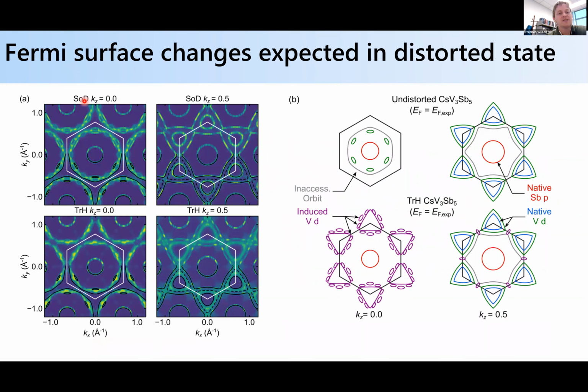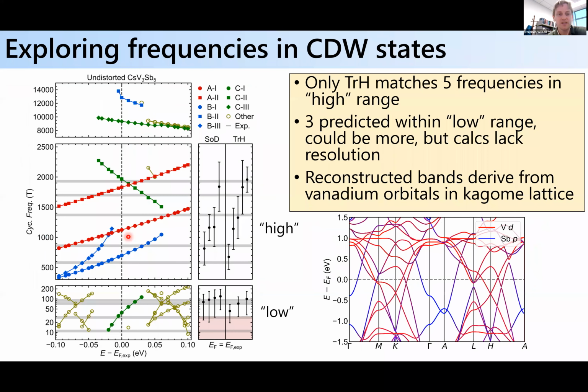And then what Sam did was calculate the Fermi surface in the candidate distorted phases, in the Star of David state as well as in the trihexagonal state. Here I'm going to show you what the surface looks like in the trihexagonal state relative to the undistorted phase. The key difference is that as you cool into the trihexagonal state, you gain a number of induced vanadium-based orbits, due to the reconstruction of the Fermi surface. You gain that both in the k=0 plane, but you also gain 1 in the k=½ plane. So what we can do is qualitatively match the number of orbits we should expect to see in each frequency window versus the candidate structures, Star of David or trihexagonal.